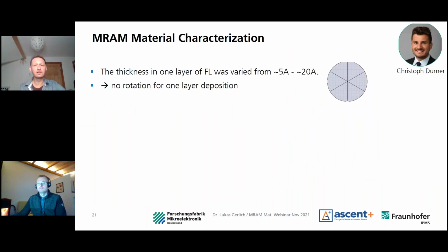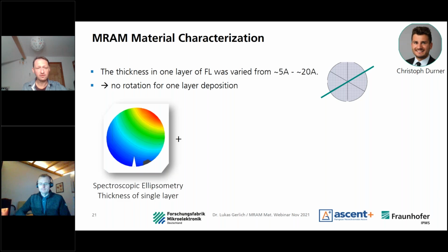So as you've seen, normally for uniformity's sake, the wafer is rotating. We can stop this, so we can vary one layer. Within the free layer, we can vary by just not rotating and have here a slope of thickness of a certain layer, and have a higher thickness and a lower thickness, for example.